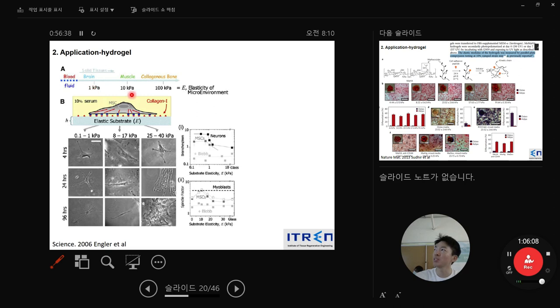So, 1, 10, 100 kilopascal. And then they mimic this stiffness using polyacrylamide gel. When they make polyacrylamide gel, they also measure the stiffness using the SS curve. Okay? And then they make around 1, 10, and 40 kilopascal hydrogel, and measure their stiffness. When they confirm it, they culture the stem cell, MSC, and look at the morphology. They check that the lower stiffness has a neural-like structure under normal growth media, but when the MSCs are cultured on high stiffness, like bone, they spread out. This is a phenotype of the bone.